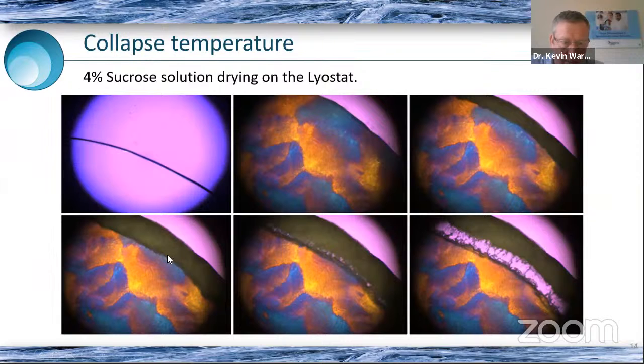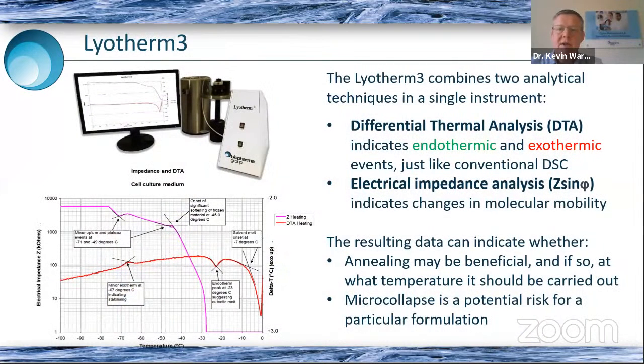first imperfections. I'm not sure whether you can see the cursor on the screen here. Just behind the drying front towards the center, we have some very, very small holes appearing in our sucrose sample. And this we might identify as being the first point of collapse, or the onset of collapse. And then as we raise the temperature further, you can see on the bottom right, we've lost all of the structure behind the entire drying front. And now we have literally got syrup as we're freeze drying the sucrose above its collapse temperature. So we can pinpoint this very accurately under the freeze drying microscope, and that's arguably the first piece of very useful, important information when you're about to consider freeze drying the material and trying to figure out what temperatures to use in your freeze dryer.